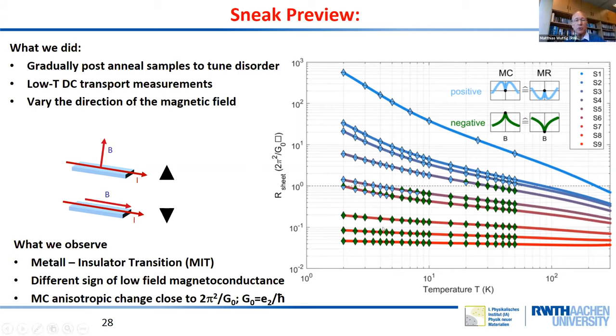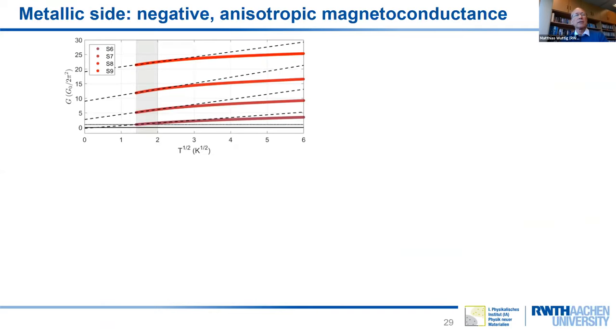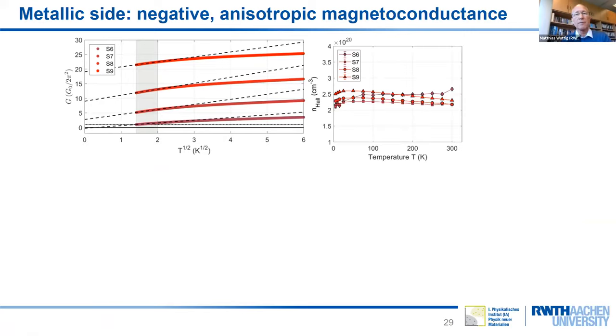And the third point is, as I will show you in a little while, that there's also a transition in the anisotropy of the magnetoconductance, as I will show you in a second. Okay, thanks. So I'm moving quickly towards the end. Now we can look, first of all, at these metallic samples. And you can see here from this extrapolation of the conductance to very low temperatures, it's pretty obvious that indeed these are metallic samples. They have a non-vanishing conductivity in the limit of zero Kelvin. We can also look at the charge carrier concentration, which does not change significantly upon annealing to higher and higher temperatures. So this is the highest annealing state.